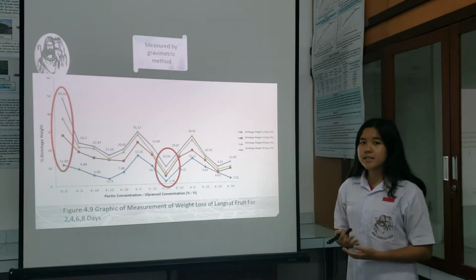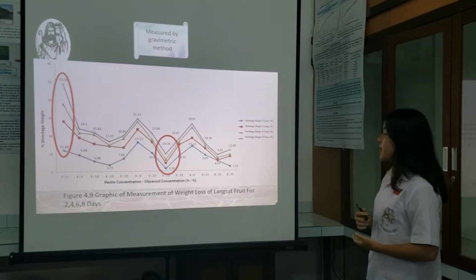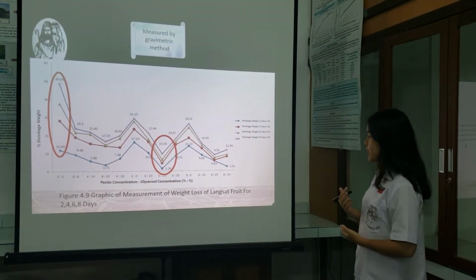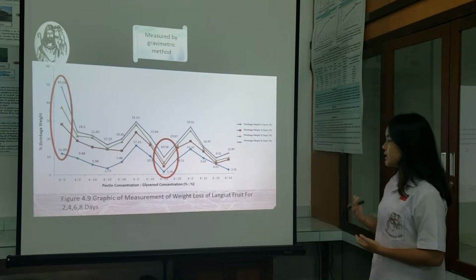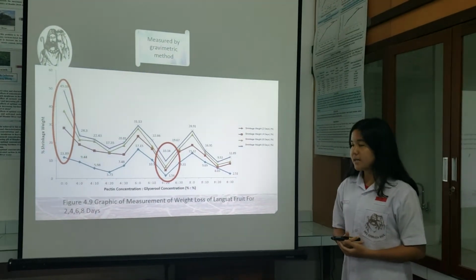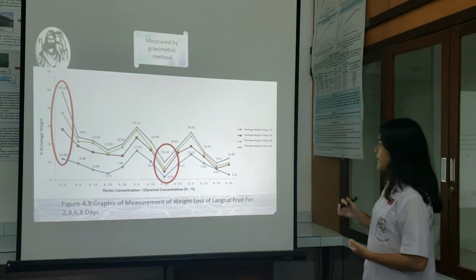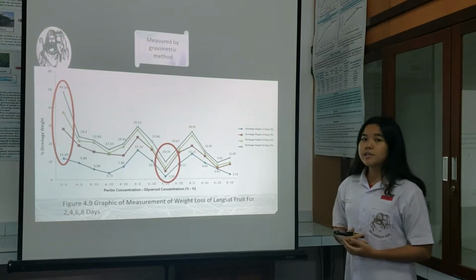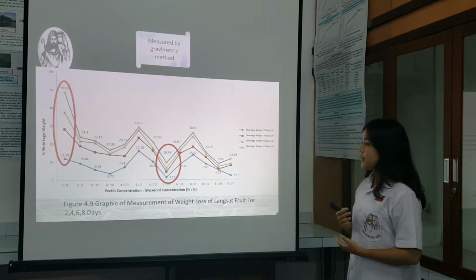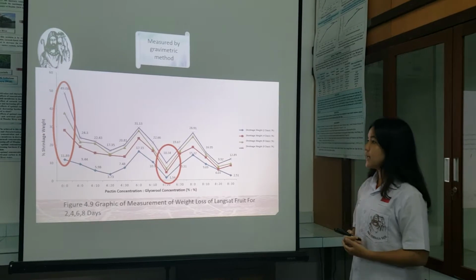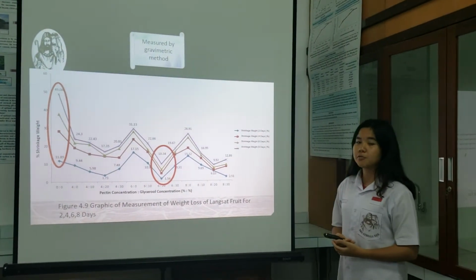My honorable judges, as we can see on this following graph, the optimal edible film variation, which is 6% pectin, 20% glycerol, when measured in 4 different times, produces a lower shrinkage rate compared to other variations. So, it can be concluded that the edible film from Pontianak orange peel-based pectin can increase the shelf life of Punggur Langsat up to 8 days.